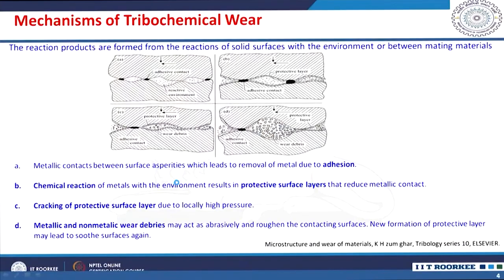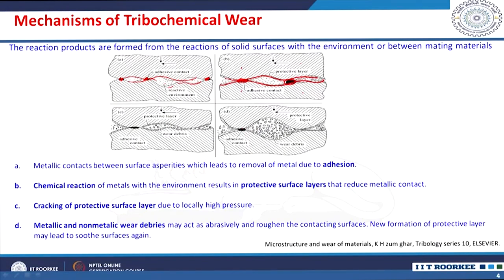the mating materials. For example, you see here for a metallic material system, the metallic contacts between the surface asperities. There are contacts with the surface asperities that lead to material removal mainly because of adhesion; this is adhesive contact. The chemical reaction of metals with the environment results in protective surface layers that reduce the metallic contact. So, the metal to metal contact is reduced, but how is the material removed? Material is removed by cracking of this protective surface layer because of the high pressure. So, there is debris forming out.